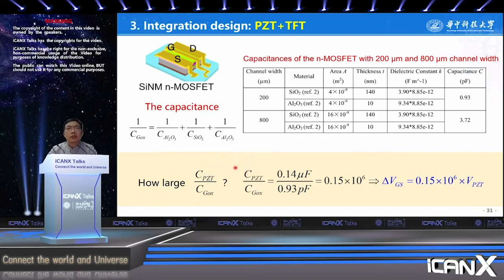For the TFT with channel width of 200 micrometers, the capacitance we get is like this one, in pF. And the 800 micrometer width one is like this one. So we can get the ratio between the two capacitors, one is the PZT, the other is the TFT. We get the ratio is about this one. From this, it makes the drive about 10 to the 6 power. It will make the drive voltage about 7 volts.